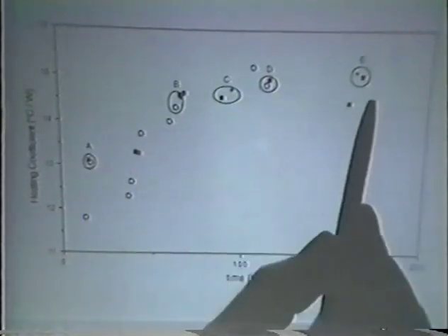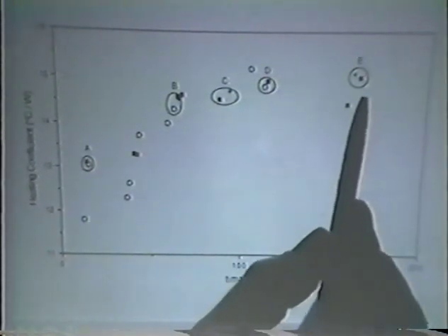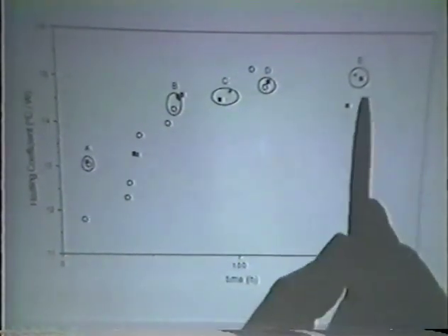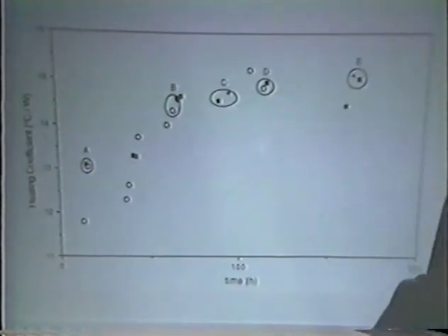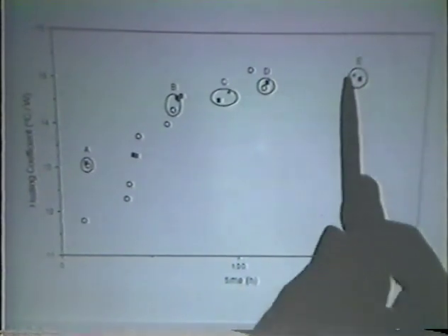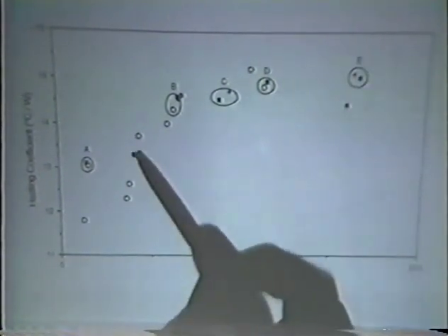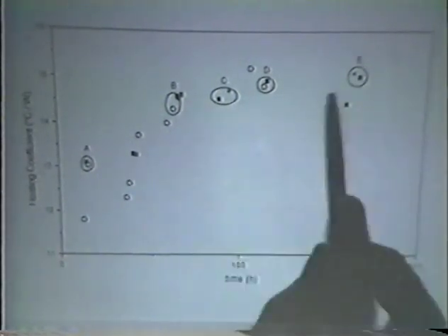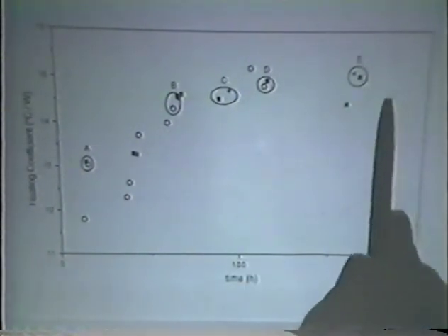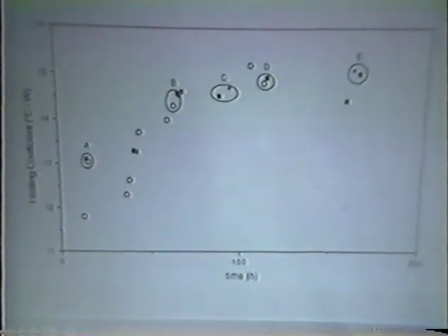An important feature to check is that if you see an event that you think is excess power, you have to ensure that it's not just a decrease in the rate of heat loss to maintain a higher temperature. And so we recalibrate all the time whenever we think we see a glitch in the temperature rise. We've never seen any evidence after the temperature rise for anything other than a change in the heat loss constant.